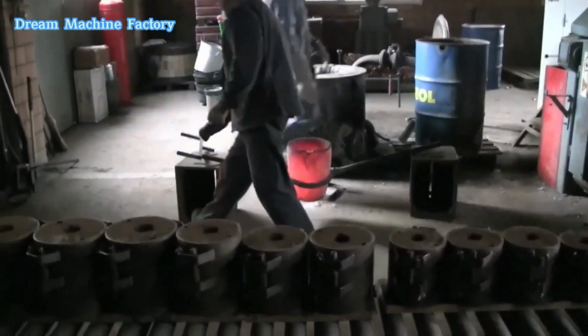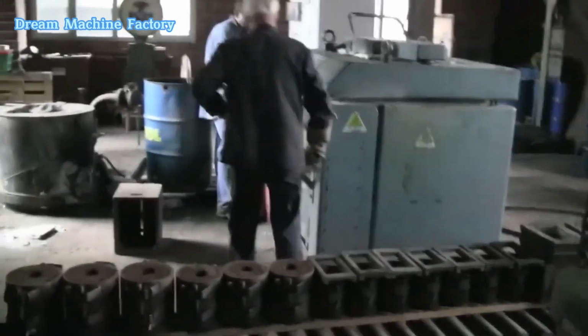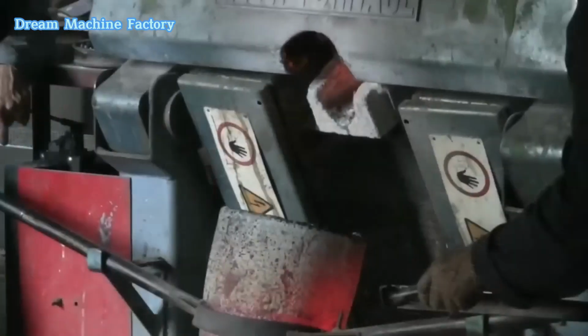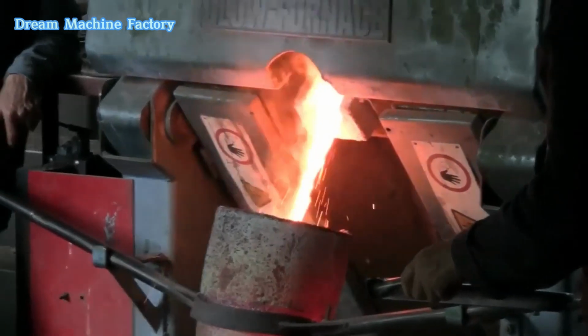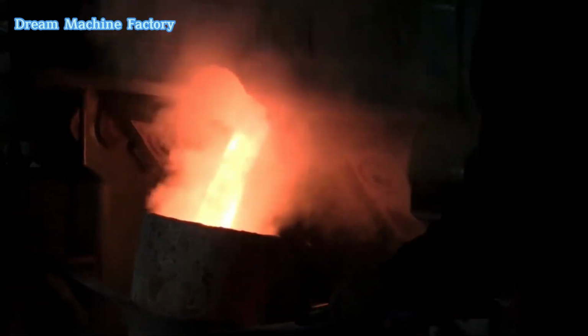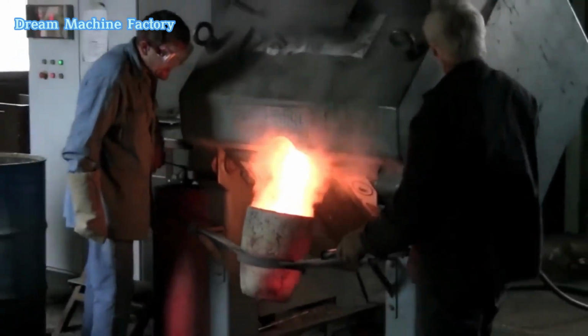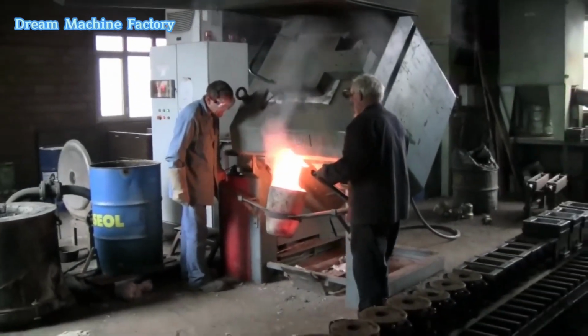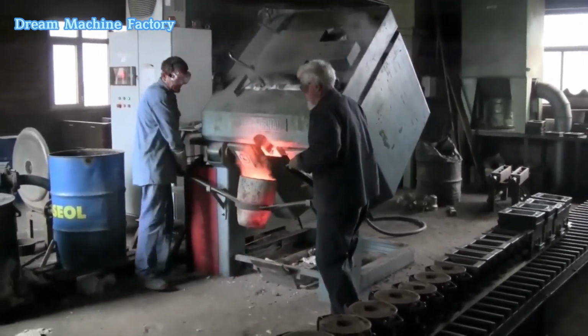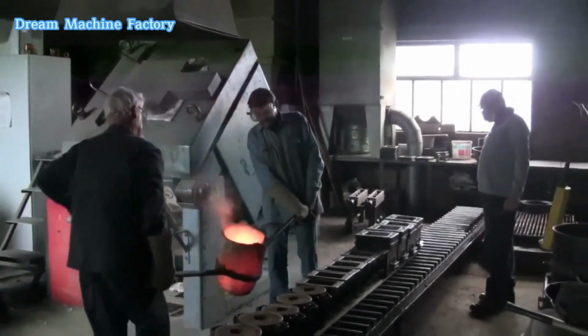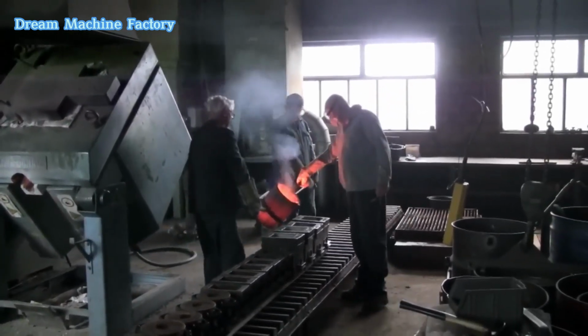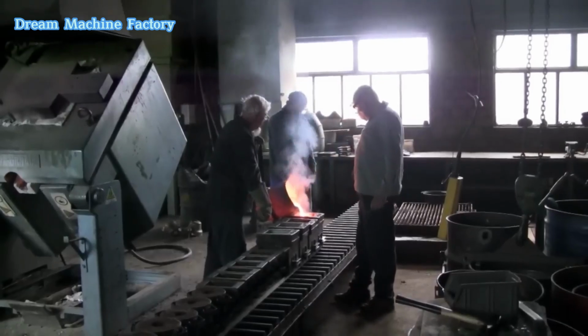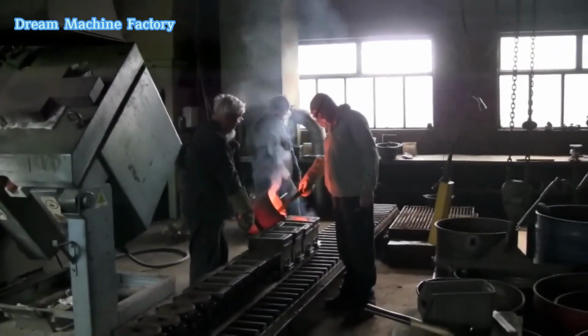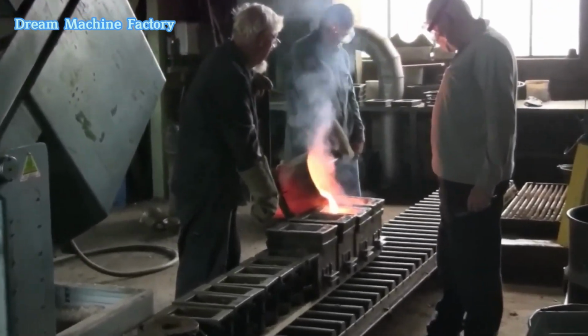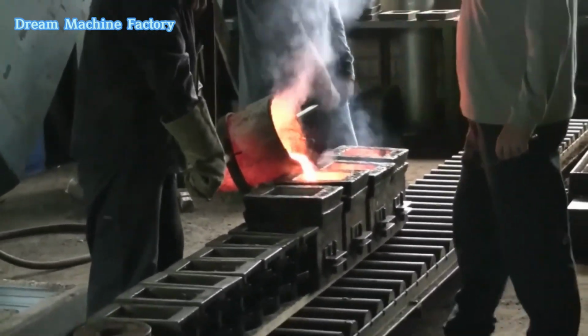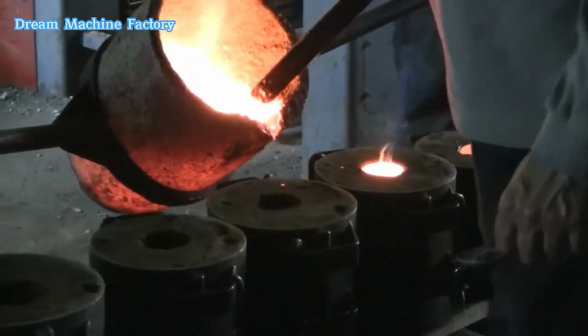Early in the morning, the furnace is heated to a temperature of approximately 1,280 degrees Celsius, 2,336 degrees Fahrenheit, to melt the bell metal, which is composed of 80% copper and 20% tin. This metal mixture, known as bell bronze, is highly valued for its durability and resonance. Once the metal reaches the desired temperature, it is carefully skimmed to remove impurities, ensuring a clean and uniform composition. The molten metal is then transferred into a pouring ladle, a process that requires precision to avoid oxidation or temperature fluctuations that could compromise the bell's integrity.